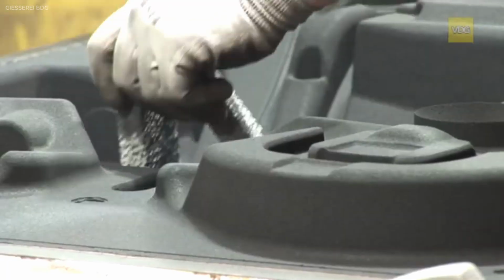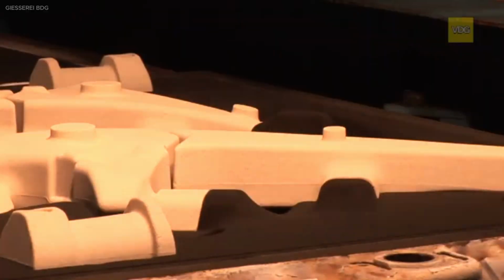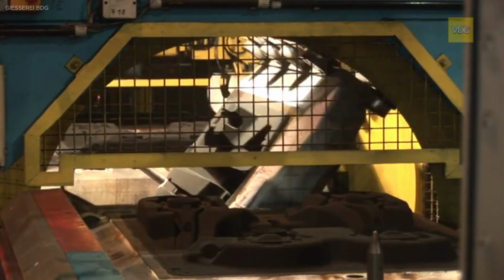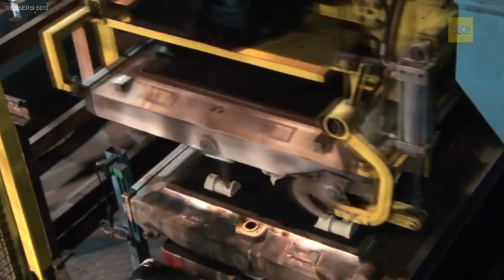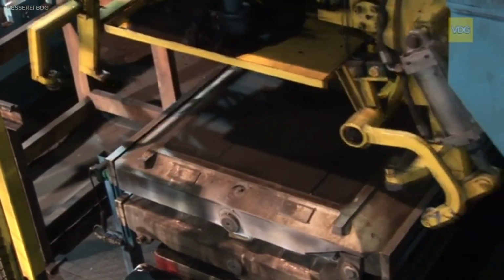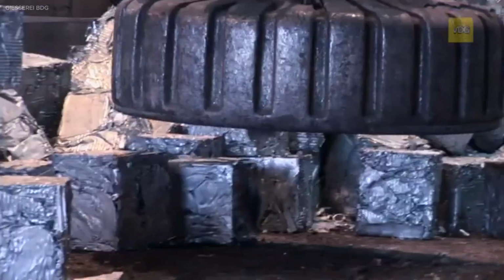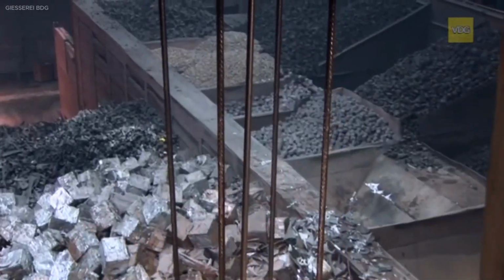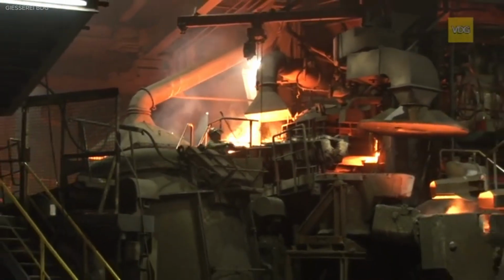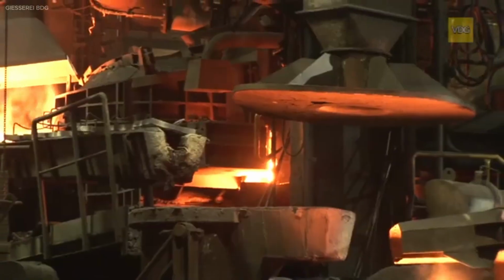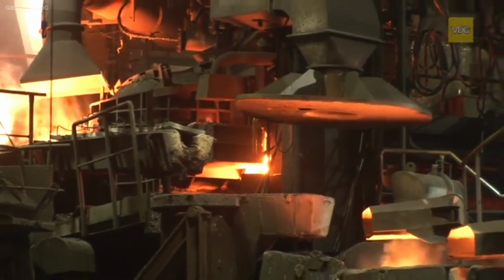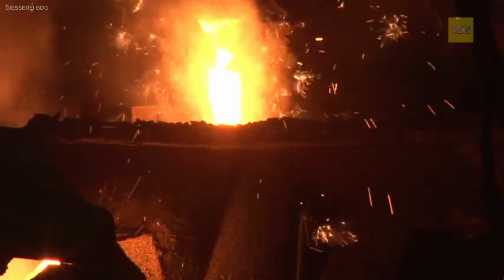A sand core, crafted in the core shop to form internal features, is inserted with a ceramic filter to prevent slag inclusion. The foundry mechanic inspects the mold, then reassembles the boxes using guide pins for precision. The mold is now ready for pouring. A standardized aluminum alloy with 11% silicon, heated to 730 degrees Celsius, is poured into the mold. After cooling to around 300 degrees Celsius, the mold is broken apart, destroying the sand form.